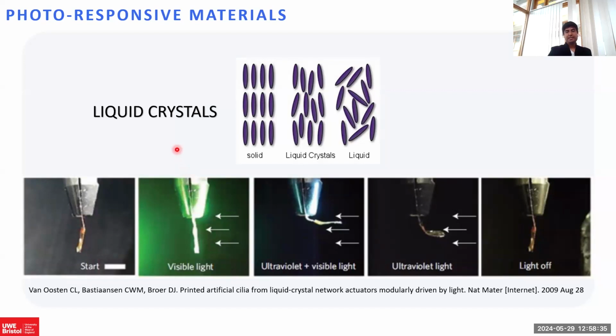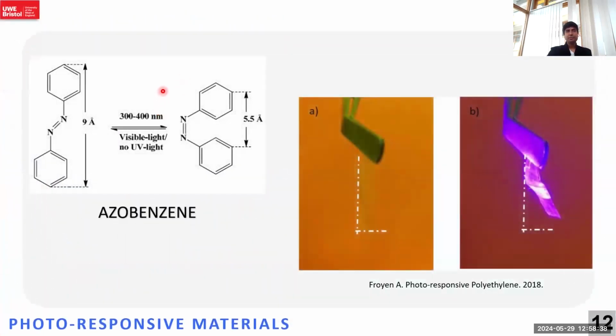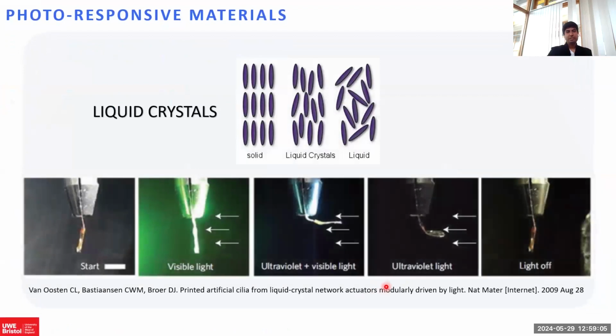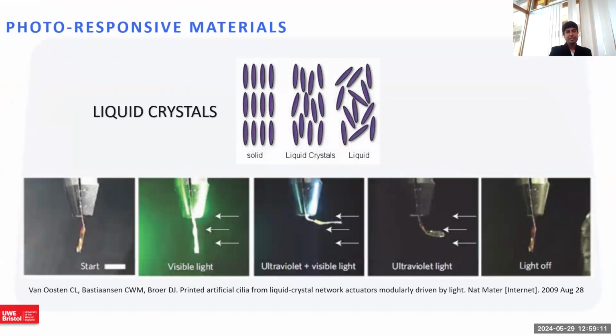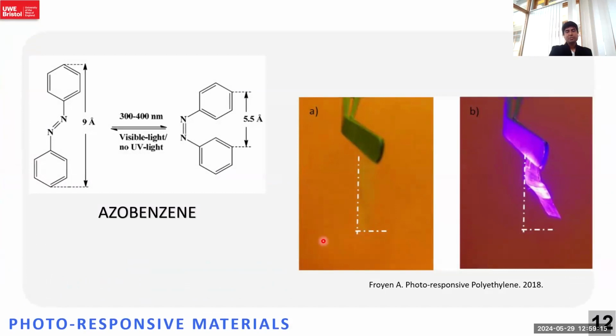But the problem with these materials is that we need to synthesize these materials within the polymers, and this requires long aliphatic chains to be characterized, because this is dichroic in nature, which means that these materials should be aligned with the polymeric chains. If these are not aligned with the polymeric chains, they cannot do mechanical deformations in that range, and we need to use a polarized light. And also this synthesis process, this complexity of the material, makes it very hard to be utilized.